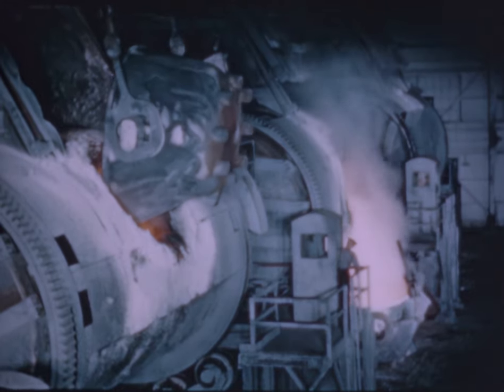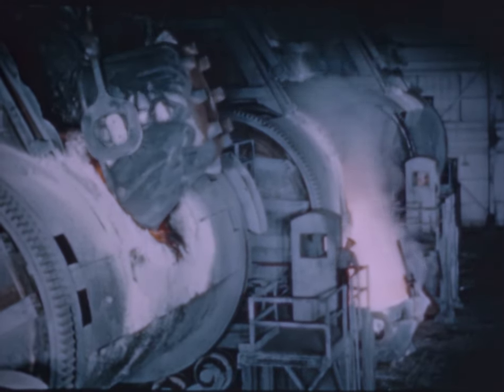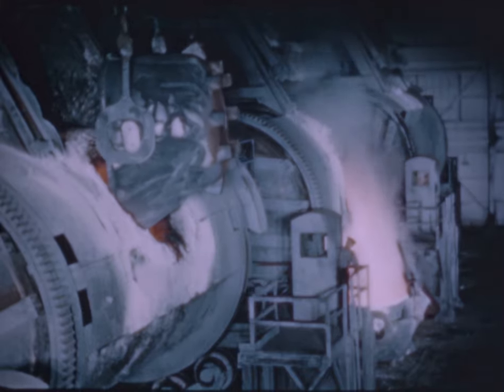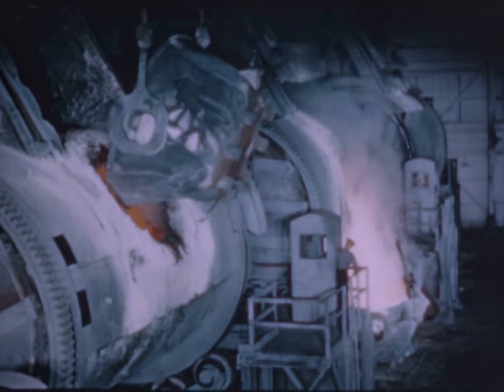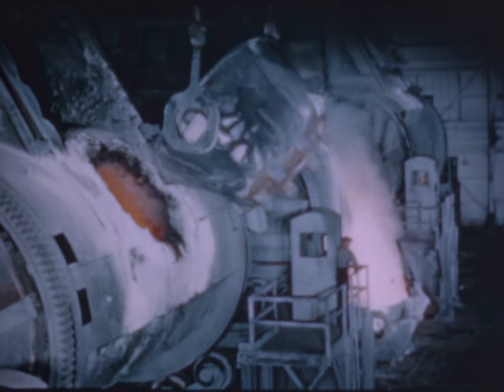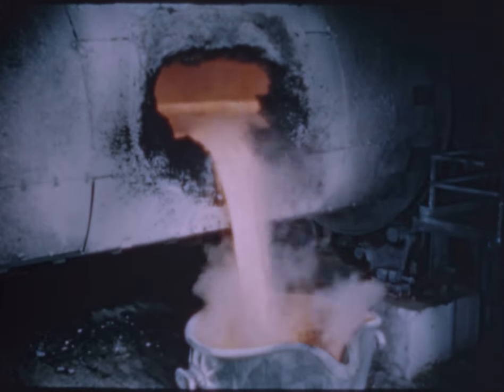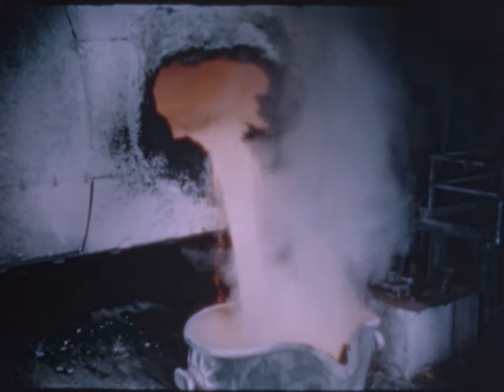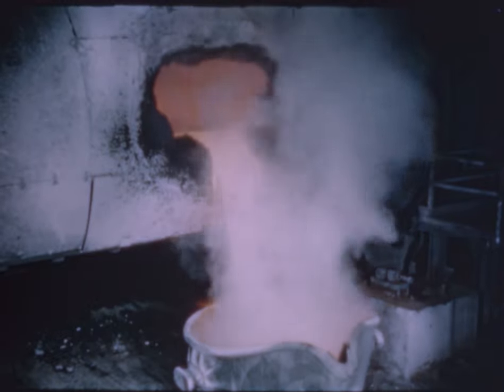This is accomplished by blowing air, under pressure, through the molten mass. Sulfur gases pass into the flue, while the iron oxide combines with silica to form a slag. Converter slag has a recoverable copper value and is returned to the reverberatory for retreatment.